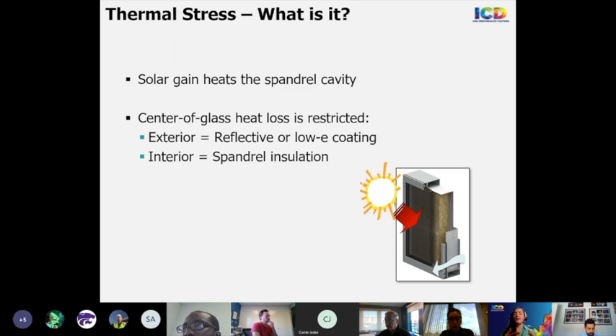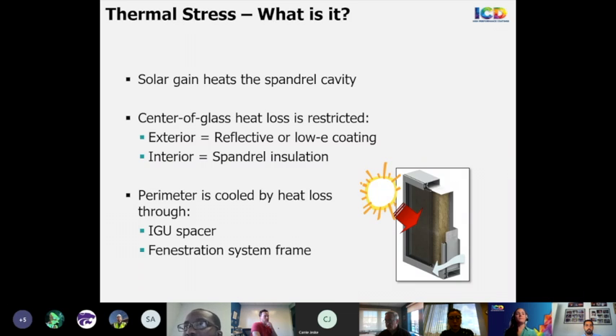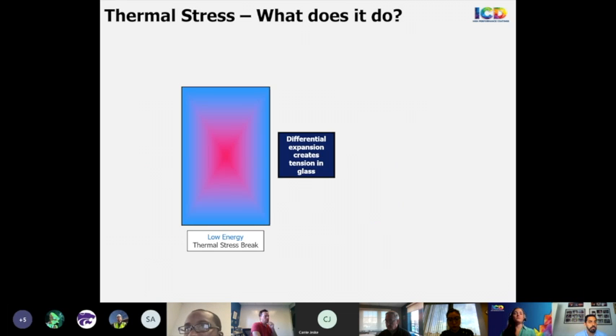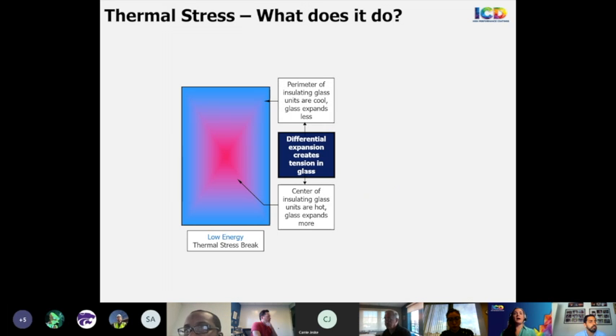So therefore, that cavity gets very hot. The solar gain, coupled with the restricted heat loss, allows the center of glass portion of the spandrel glazing to become very warm. And at the same time, the surrounding framework chills the perimeter of the glazing, so the warmer center of glass area expands relative to the colder perimeter, creating tensile stress. And it's when the stress exceeds the strength of the glass that breakage can occur. So here is a visual of the center of glass area, which gets hot from solar gain, surrounded by a perimeter area that is cooled by heat loss through the framing, which can result in a crack forming.